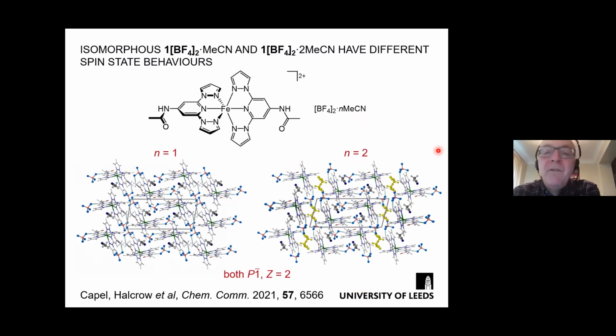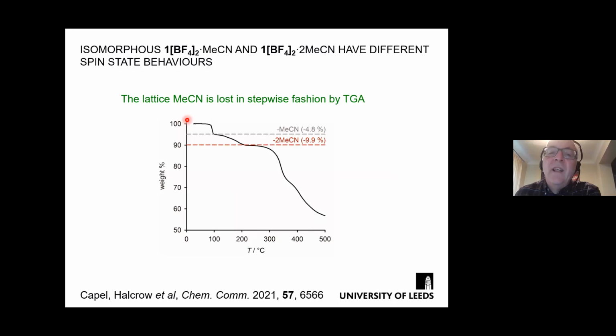What is a bit more informative are the nitrile solvates. So this is the acetonitrile solvate of this crystal. And in fact, we can isolate 2 solvates with 1 or with 2 molecules of acetonitrile in the lattice. And they are isomorphous, same space group, same unit cells. But this solvate has an extra equivalent of acetonitrile squeezed into a pocket inside the lattice. And in this solvate, this yellow solvent molecule is gone, but everything else is the same. And in fact, you look, the first equivalent of acetonitrile is lost quite easily. The second equivalent is retained much more strongly. So you can study the 2 solvates quite separately.